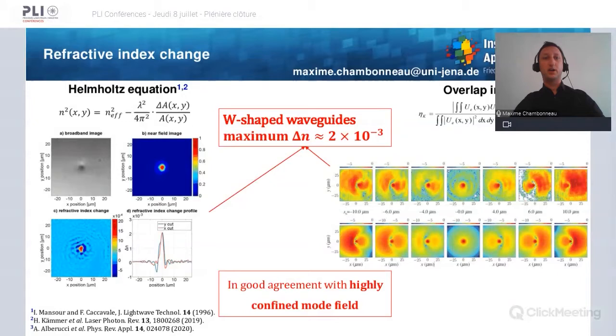Okay, so what is the refractive index change associated with the waveguides we have written? Well, to answer this, we rely on two different methodologies. The first one is known from the 90s, relying on an inverse Helmholtz equation, as you can see here. And a second method we have developed relies on the overlap integral for the waveguides, as well as a beam propagation model. And then we could compare basically the experiments to some simulations by shifting transversely the waveguide with respect to the input continuous beam. Both of these methods conclude on some refractive index change on the order of 10 to the minus 3, which is in very good agreement with highly confined modes.